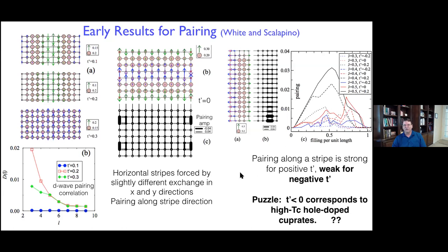Okay, so that's all pretty clear, except for one thing. The pairing response is strong for positive T prime and weak for negative T prime. But T prime less than zero is supposed to correspond to the high TC hole doped cuprates, which have stronger superconductivity. And so that's exactly the opposite of what we would have expected. So there's a puzzle. But that summarizes the result.